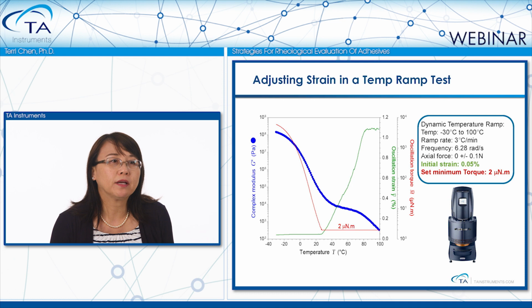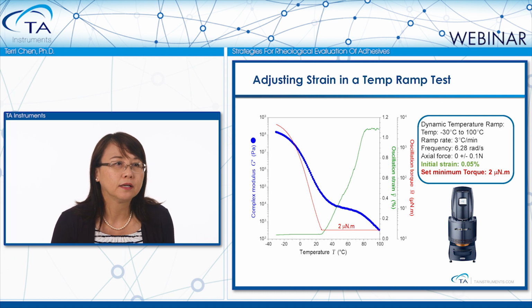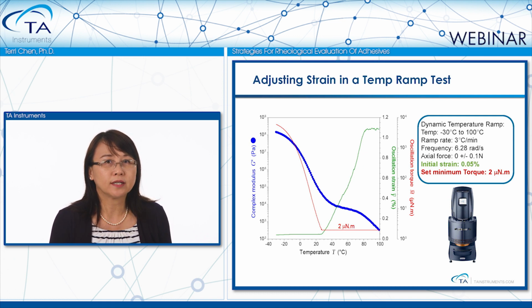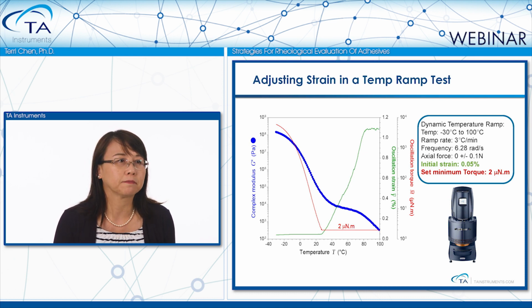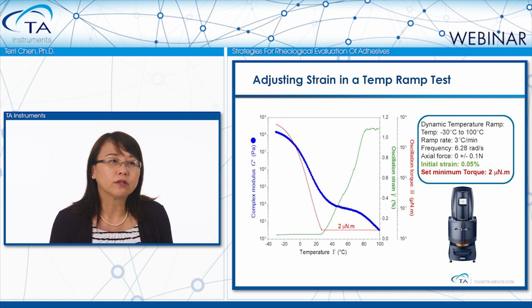This is a temperature ramp experiment on a non-crosslinked PSA sample. The measurement is from minus 30 degrees C up to 100 degrees C with a heating rate of 3 degrees per minute. The initial test strain was set at 0.05%, which was within the linear viscoelastic region of this sample and also appropriate for the measurement at the initial low temperatures. As the temperature increased up to above the glass transition, the sample became a lot softer.